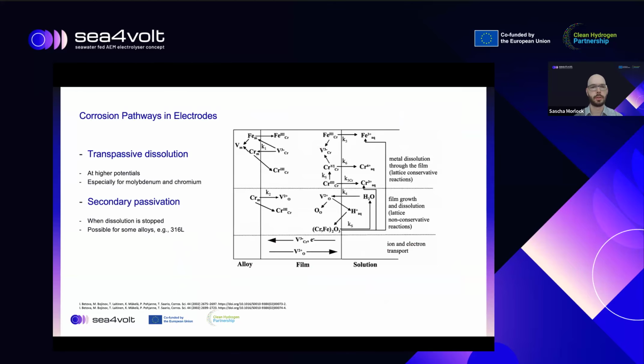please. Transpassive dissolution is also an important aspect when it comes down to corrosion in electrodes in seawater electrolysis. Transpassive means that at first the electrodes are stable, but if you apply too high potentials, then some elements can be leached out. This is especially critical for molybdenum and chromium. And in some cases, you can see a secondary passivation, meaning if you reduce the voltage again, the dissolution is stopped and you get another passive layer. However, this is not as stable as the initial passivation, so it's still undesired. Next slide,